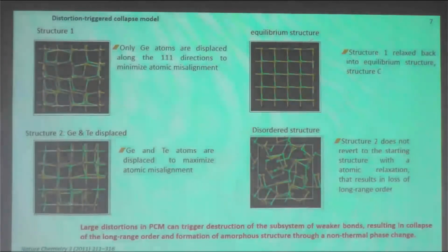So next model, it's based on the distortion-triggered collapse model. This model was studied solely in computer simulations. Here the authors, Kolobov and Tominaga, proposed two structures. In structure 1, the germanium atoms were displaced along the [111] directions to minimize atomic misalignment, and in structure 2 they allowed germanium and tellurium atoms to displace to maximize atomic misalignment. Then they relaxed both structures, and they found that if we have a minimum distortion of